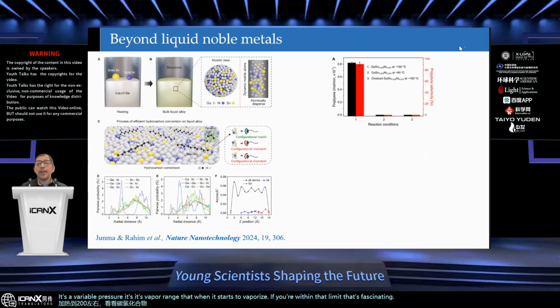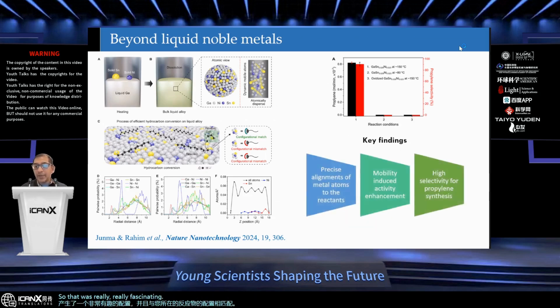Now, one of the surprising things that we found was that when we added these two metals, there is a configurational match, because we looked at a range of different hydrocarbons, and every time we found that we are producing propylene. So this catalyst was chopping off the hydrocarbon chain in a very specific manner, which you can only think of in the way an enzyme works. That's a very specific way that an enzyme works, that doesn't let other things enter a pocket. It's something like this: the metal produces a very interesting configuration, and that matches with the configuration of the reactant that you're using. So that was really fascinating, and the precise alignment of the metal atoms to the reactant was one of the key findings of this one.